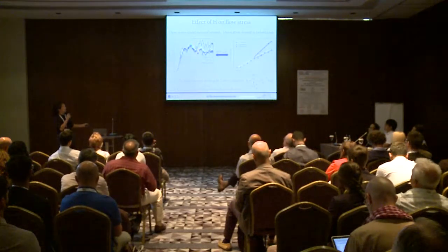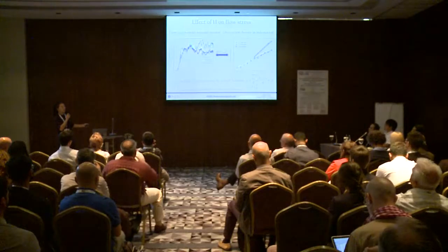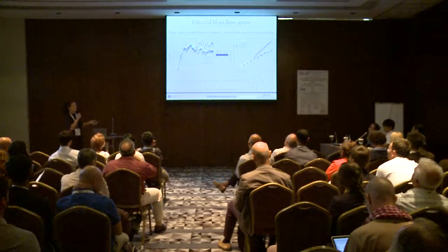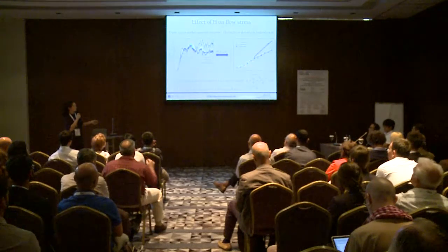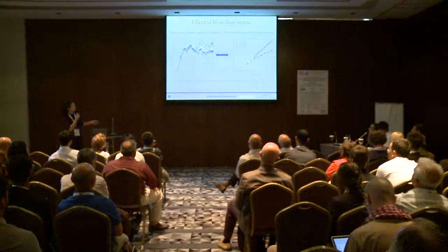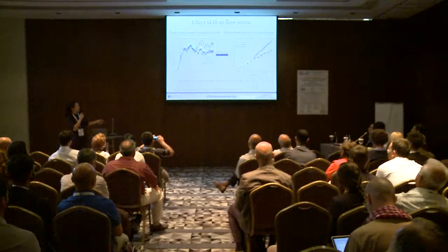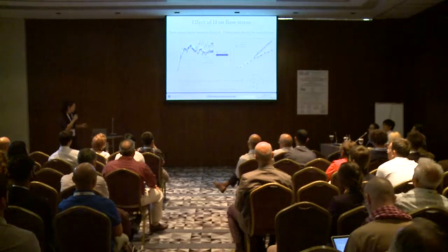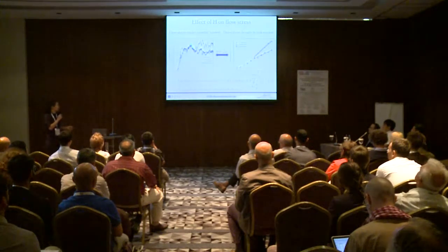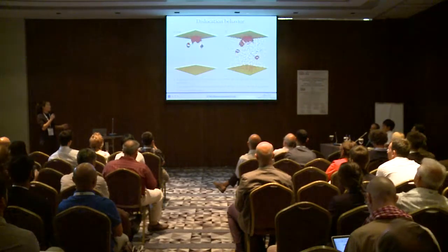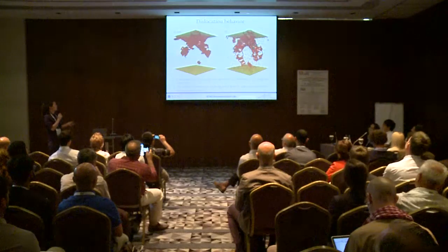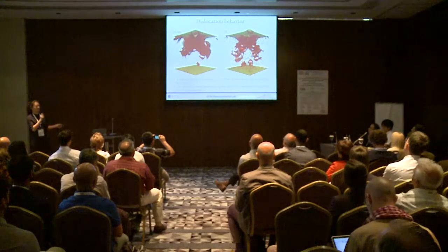This also indicates a lower dislocation density, which is confirmed by the analysis of the dislocation density curve. At small depths it is similar, while only at higher indentation depths does hydrogen induce a lower dislocation density. Here is an animation showing the whole process, comparing the hydrogen-free and hydrogen-charged cases.